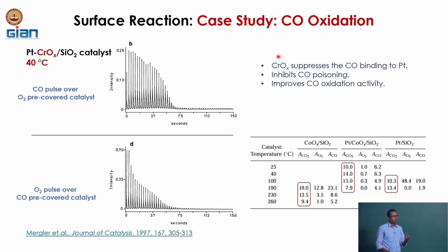CO binds to platinum strongly, and at low temperature, if a significant number of platinum sites are taken up by CO, then that hinders the oxygen adsorption. But at high temperature, just because the binding energy is lower, because desorption is more favorable, we do not have that kind of issue and the catalyst becomes active. But if we add chromium oxide to this platinum as a promoter, the chromium oxide suppresses the CO binding to platinum, and hence we can still see the product formation or the reaction happen even at a much lower temperature, which was not happening previously.